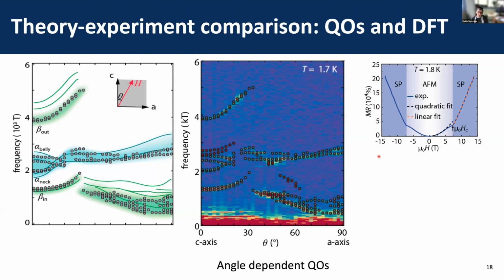But in addition to the quantum oscillations, our magnetotransport measurements have also revealed very large magnetoresistance. And here's a measurement at low temperature, 1.8 Kelvin, up to 14 Tesla, with the dark shading here corresponding to the saturated paramagnetic state, where you can notice a number of things.